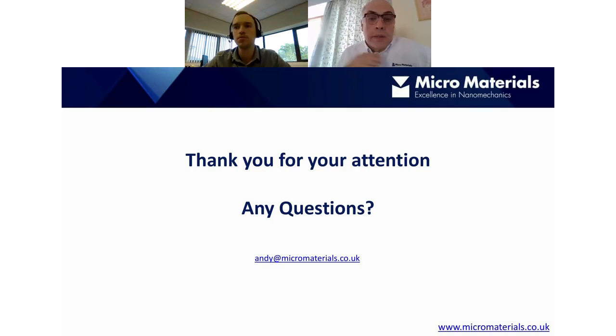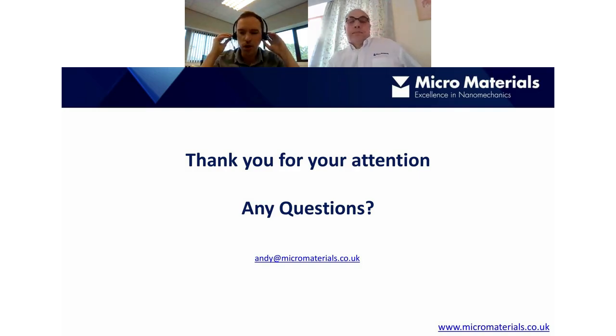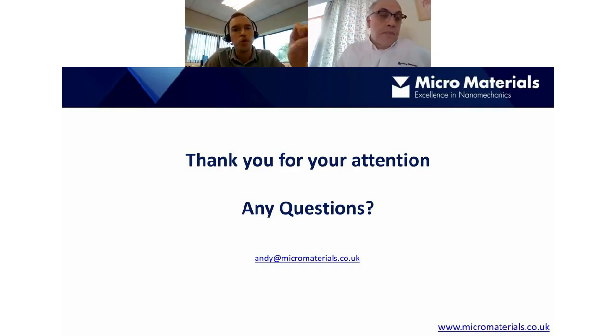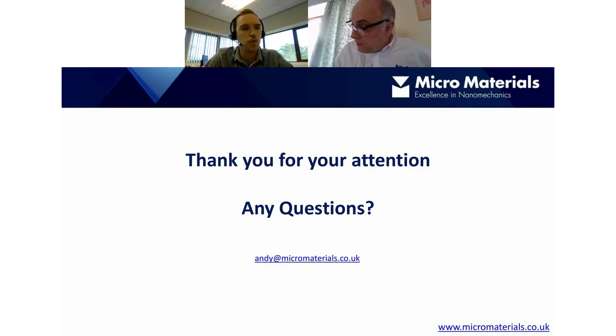The first question has come on the screen now for you, Andy, from Gabor. If the material is anisotropic, how can reduced modulus be obtained? Well, with reduced modulus, we're just measuring the modulus at the point of the indent. Of course, the reduced modulus of the material may change. If it's an anisotropic material, multi-phase material, there can be variations in reduced modulus and therefore elastic modulus. So the only consideration is when we're converting between reduced modulus and elastic modulus. All we need to know essentially is the Poisson's ratio and the elastic modulus of the indenter material, and also the sample as well. And again, it may be difficult to do that with some samples, especially if they are, say, multi-phase.